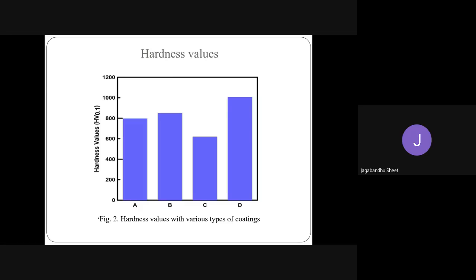When the NIB is the outer layer, a very hard phase is found. Comparing A and B, where A has NIP as the outer layer, the hardness value is lower than B, which has NIB as the outer layer. Coating C is considered to have very low hardness among the multi-layer coatings, since NIP is the outer layer. But for the multi-layer coating with NIB as the outer layer, with four successive layers, the hardness value is higher.